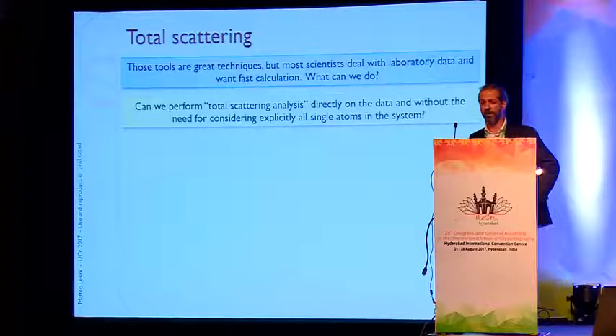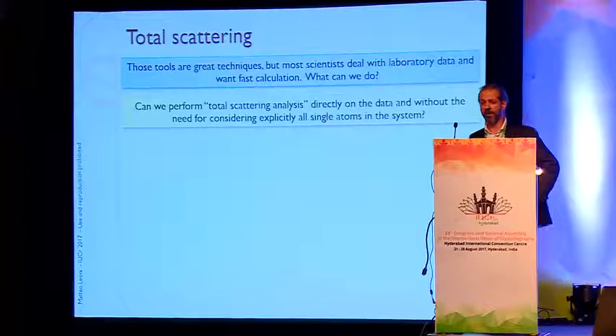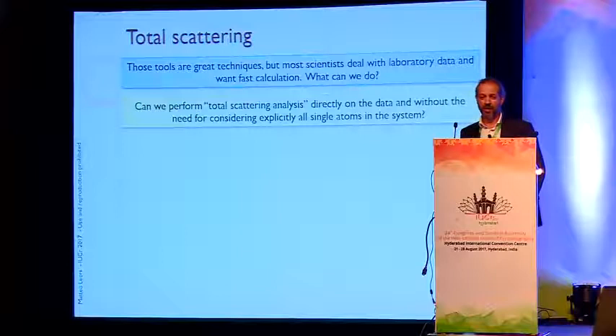Great techniques give excellent results published in top journals, but most of us have a normal diffraction pattern from a laboratory. The question is, what should we do with that? It's too short a Q range to get a PDF, and if you want to analyze a reasonable size system, the Debye equation is too slow. Can we get in between? Can we do total scattering analysis using tools that are not those, with the data that we have?